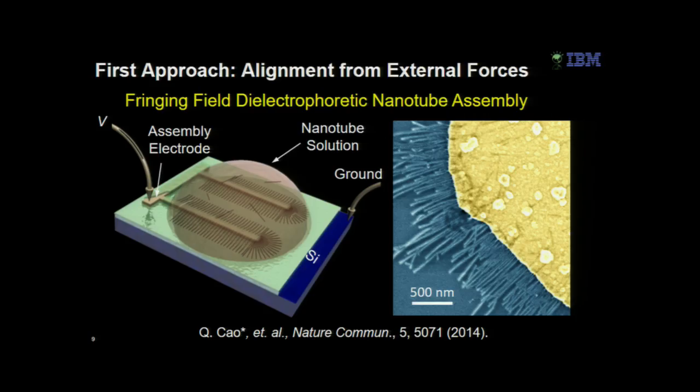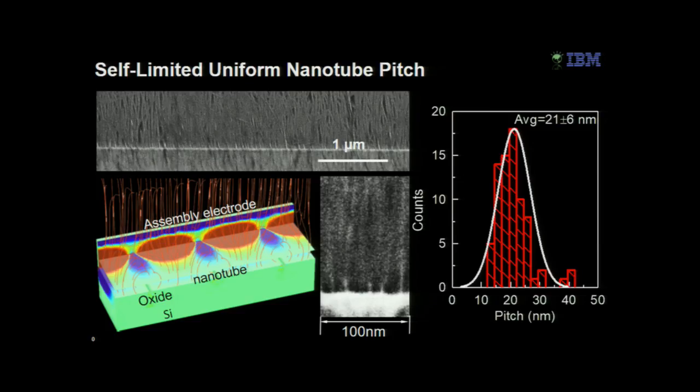In this example, we can generate well-ordered line arrays of semiconducting nanotubes using the alternating fringing electric field between this assembly electrode and the global silicon substrate. A very nice feature about this method is that the nanotube pitch is very uniform because it's self-limited. The deposition of one nanotube effectively screens the fringing field around it, leading to a self-limited nanotube density or pitch at around 20 nanometers, as can be observed in both experiment and also finite element